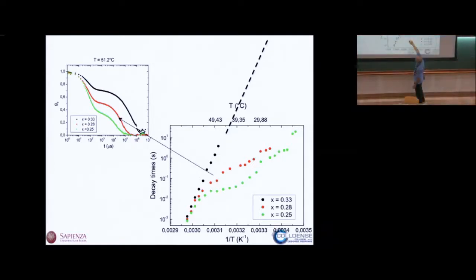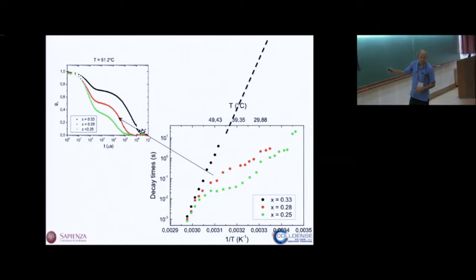The swap region is more complicated to describe dynamically, but at the very end, the typical time scale is the evaporation of the toehold. Right? The toehold touches, does all the random walk, and then at the end it has to evaporate. And so the typical time that controls the swapping process is the evaporation of this bond. And so now this has a slope 4, and this has a slope 11. So we have not really created a DNA-mer because we have not been able to stop entirely the dynamics. We have a dynamic which still goes on, but on a much faster scale due to the swap.